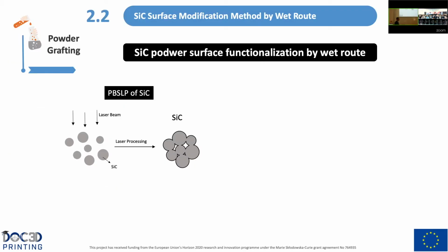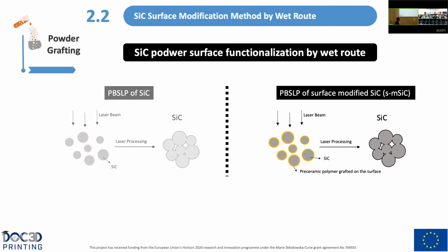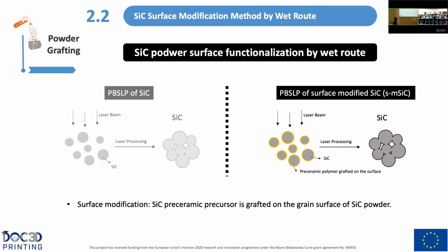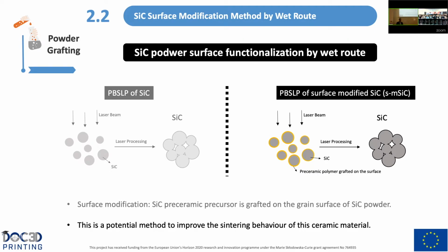So now it's time to introduce the technical scientific approach of this PhD. Now we have optimized this process, as we have seen, but what we want to do is to graft a pre-ceramic polymer, as we said, to the surface of the silicon carbide powder. For this, we need to perform a surface modification, in which the silicon carbide pre-ceramic precursor is grafted on the grain surface of the silicon carbide powder. And this is a potential method to improve the sintering behavior of this ceramic material.